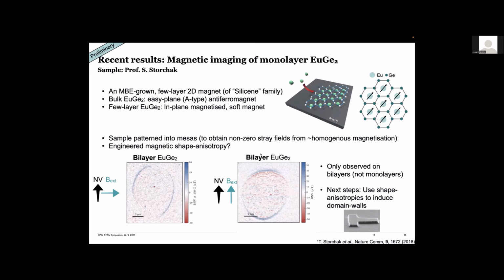So here, this is again data on a bilayer. It's the same sample you've seen before. This is the circular sample, but we also prepared ellipses, which you see here. And the remarkable thing is that, so you have to realize that the magnetization in this sample points in this vertical direction. So it just follows the external magnetic field. And it's something we've verified with a couple of independent sample preparation steps.